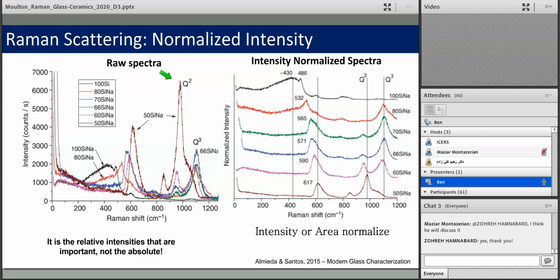If you compare all these spectra just by their raw intensities, you come to a very misleading view of what's happening in your sample because the intensities are so different. The 50% sodium sample has 4 times the intensity of the pure silica. Normally what you do is some sort of normalization, either area normalization or, I recommend, intensity normalization, where you make the maximum intensity equal to 1, and then you plot the spectra offset. So you can see the vibration here is equal to the vibration here, and you can get a much better comparison of how these peaks shift and grow or do not grow as you change the composition, for instance.